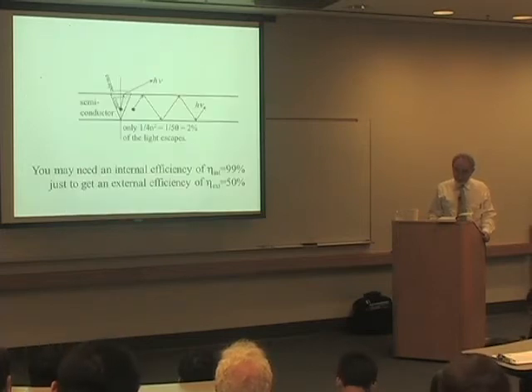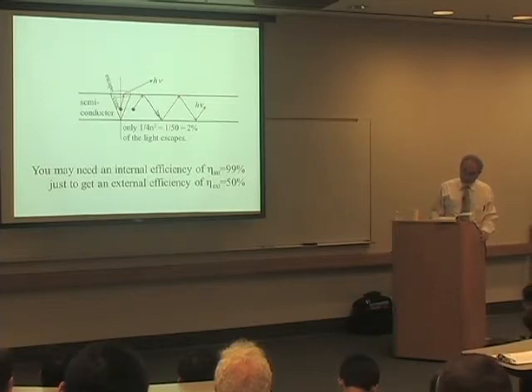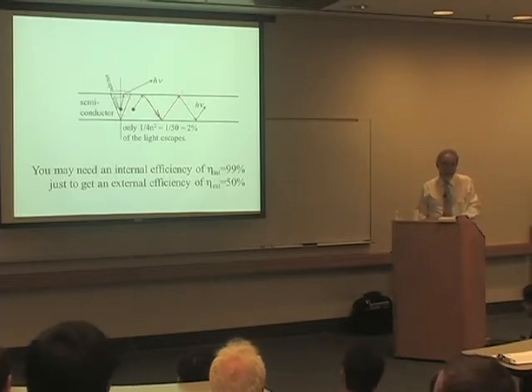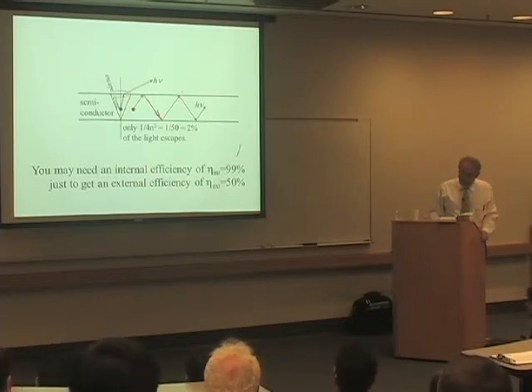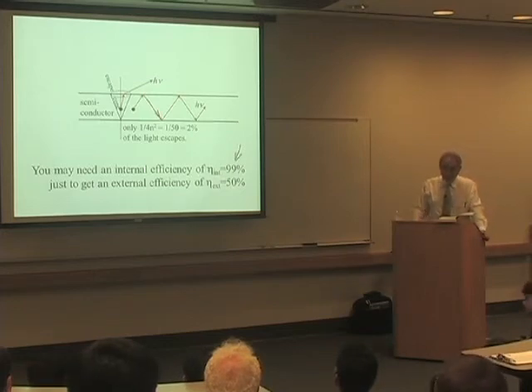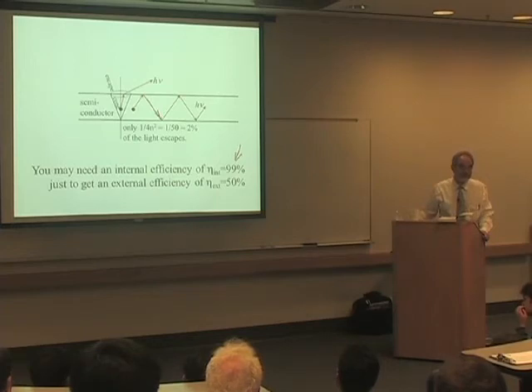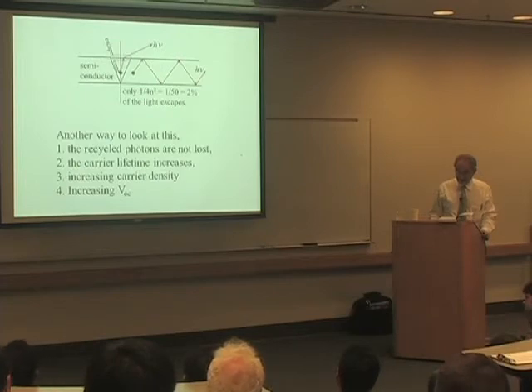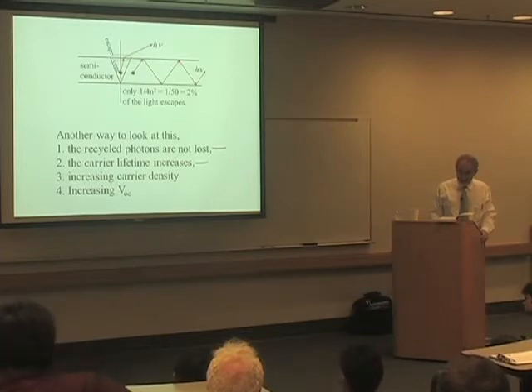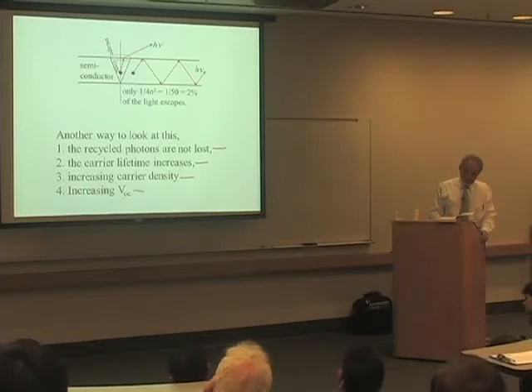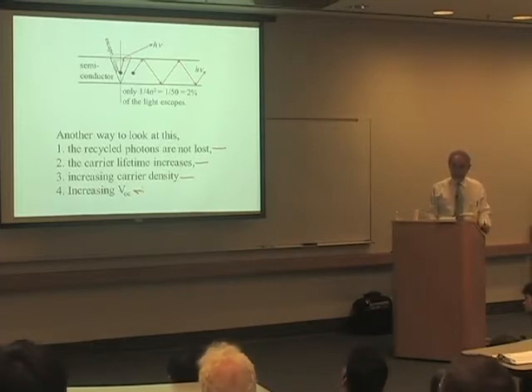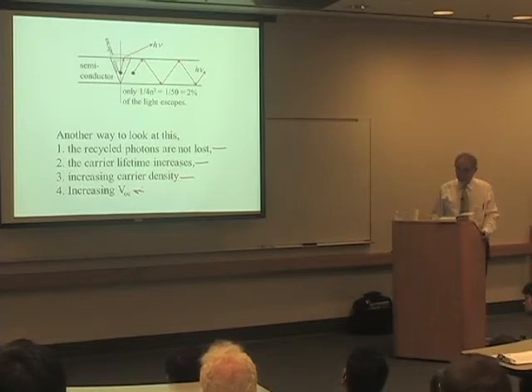Now, why is it so hard to achieve the Shockley limit? Well, because of all the light bouncing around internally, you maybe have to recycle the photons many times. You might need an internal fluorescence yield of 99% just to get an external yield of only 50%. And so it puts a tremendous burden on the internal fluorescence. Another way to look at it is to say the recycled photons are not lost, therefore the effective carrier lifetime increases. If the lifetime increases, the carrier density increases, and the open circuit voltage is kT natural log of the carrier density. So that's another way of saying the same thing.